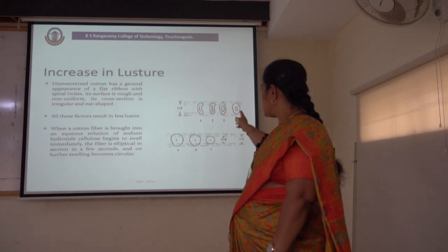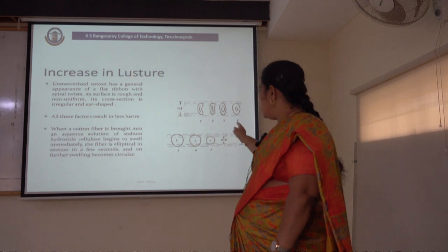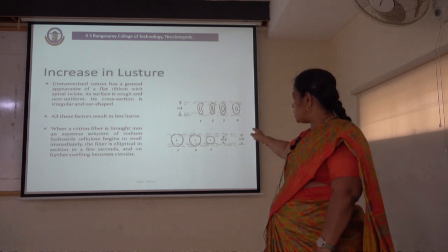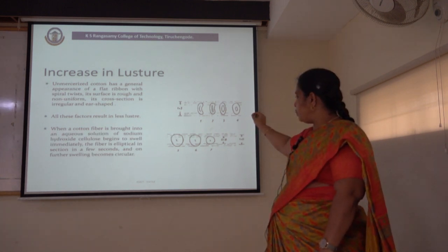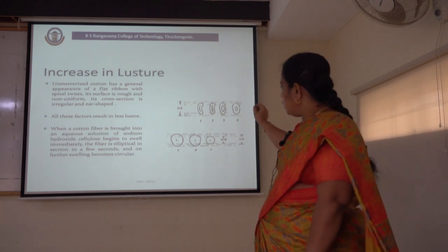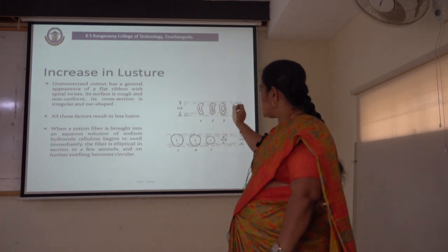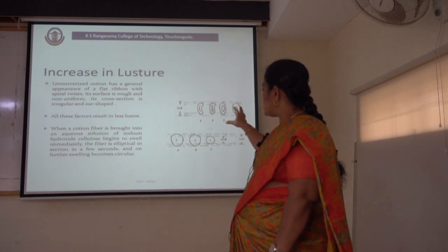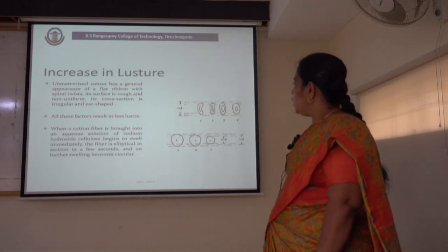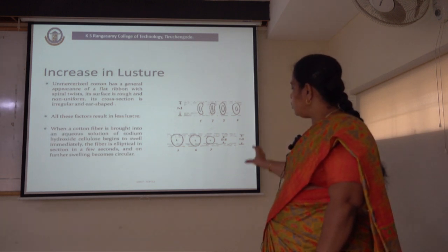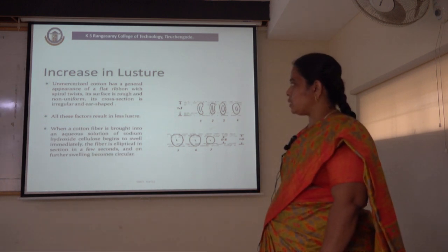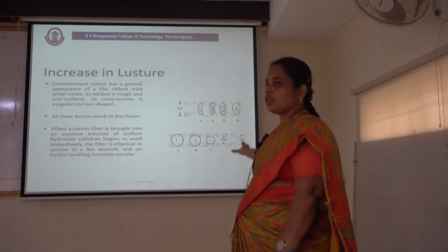This change from the flat ribbon to the circular shape is illustrated gradually in structures 1 through 7. In structure 1, convolutions are seen, whereas in the final 7th structure, no convolutions are present. The fiber is initially in the kidney bean shape and finally in structure 7, the fiber is in a round shape. Only because of this change — the change of cellulose from cellulose I to cellulose II and the change of external structure from kidney bean shape to round shape — the structure of the cellulose is improved, resulting in good luster, improved dyeability, and enhanced strength of the fabric.